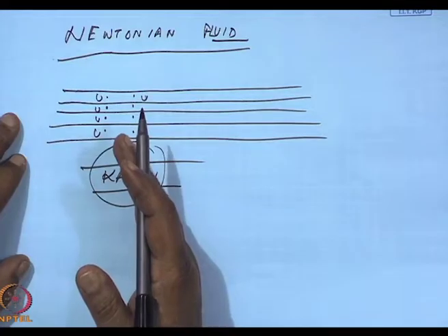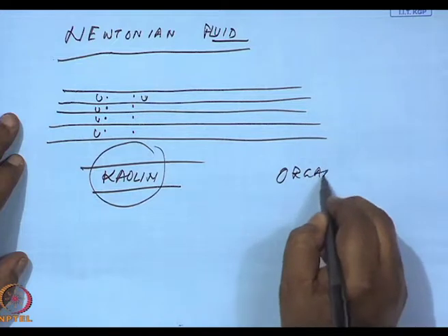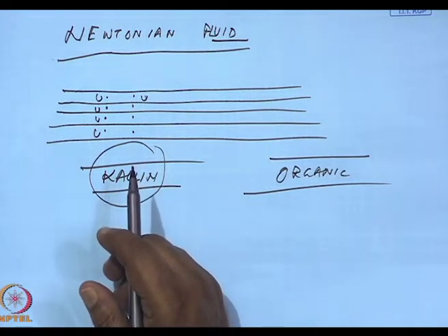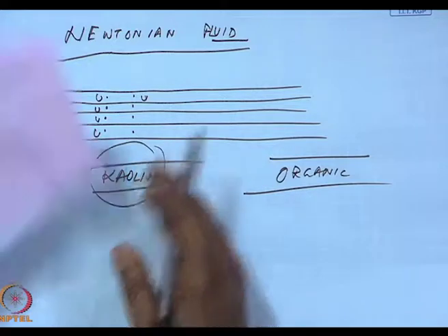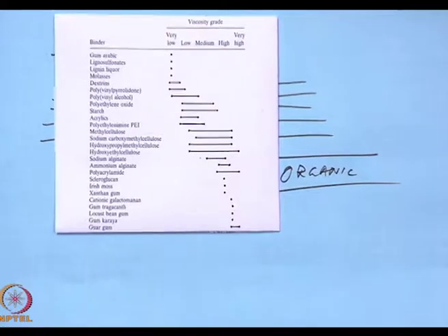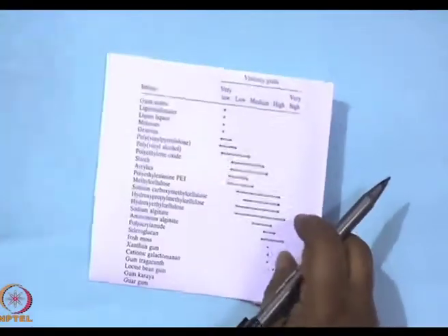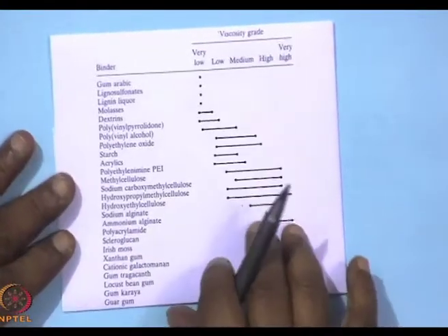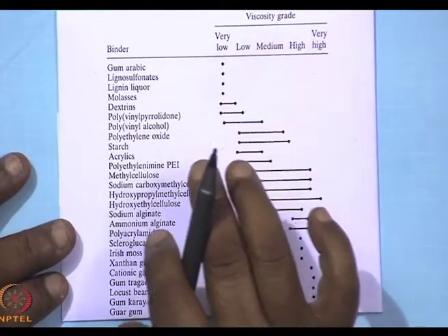But this certainly cannot be used to fabricate an alumina tube which will blow oxygen in molten iron or steel, where the temperature shoots up to 3000 degrees centigrade. If I am going to fabricate an alumina tube through which I can blow oxygen into molten steel, I cannot afford to have any glassy phase. So, there the binder has to be an organic binder which will not form a glassy phase. You see, there are various types of organic binders which are available. Let me take this paper off and let them focus on it. Yeah.